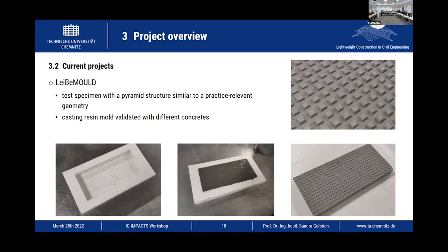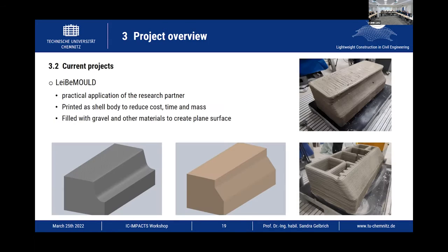For the validation, a test specimen with a pyramid structure corresponding to a practice-relevant geometry was implemented, and the resulting casting resin mold was tested with different concretes. Here you can see a practical application of the research partner. It's a curbstone with a defined surface texture.